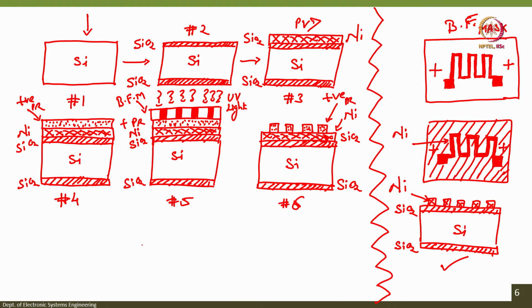So, after this what is the next step? We go for the hard bake, and then after hard bake what will happen? The photoresist will become stronger. Once the photoresist becomes stronger, we develop this wafer in nickel etchant, okay, because this is nickel. So, we develop this wafer in nickel etchant. Upon developing this wafer in nickel etchant, what we will get?